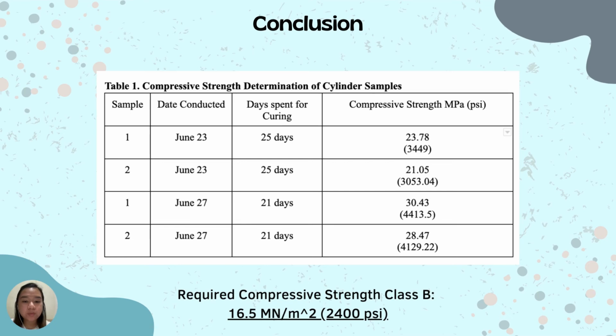So the required compressive strength for this one, according to the Class B of the DPWH Blue Book, is 16.5 MPa or 2,400 psi. And as you can see, all samples have passed the compressive strength for this experiment.